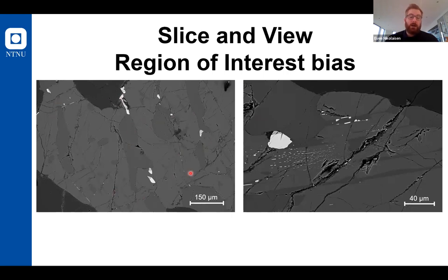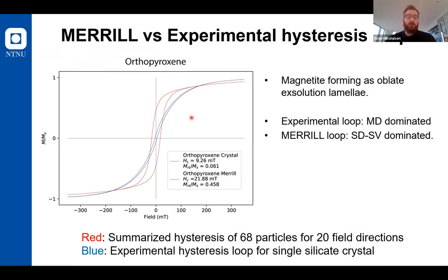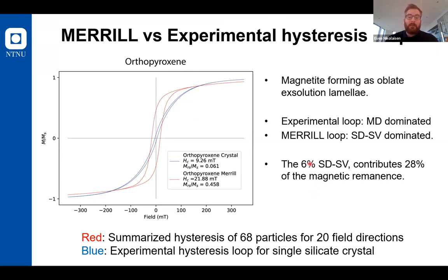When you are measuring a full or complete silicate crystal, you take everything that's included. But this is way too big for us to actually analyze, and the only regions that we can extract is what you can see here outlined in red. So you get quite a large offset between the different hysteresis curves. We can look at how much of our calculated hysteresis is actually included in the measurement. We did this by adding a multi-domain signal to the red curve, and estimated with the best fit that the micromagnetic calculation actually contributes about 6% of the overall measurement.